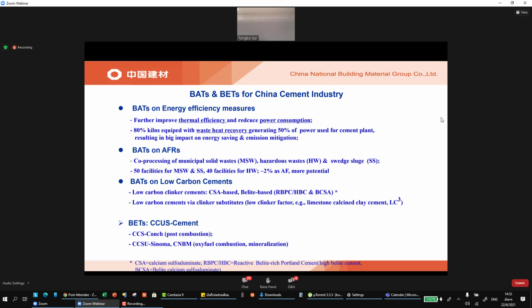I will also mention in this presentation the LC3, the limestone calcined clay cement. Just as our PhD colleague presented, we are more or less on the same track of using the same solution, the flash calcining system, to calcine the clay to make the low carbon cement more efficiently.